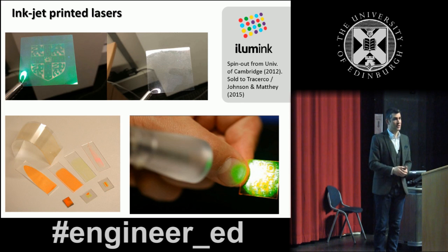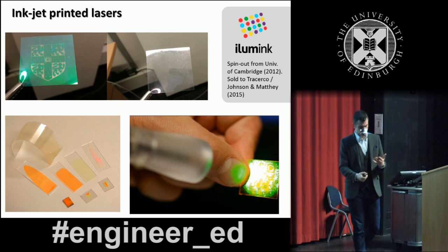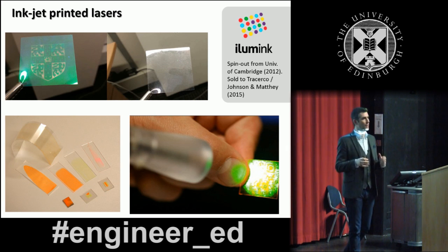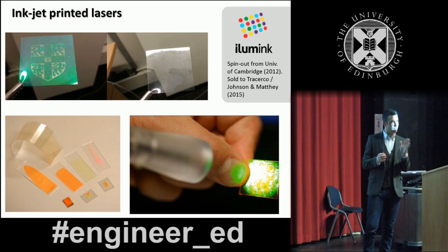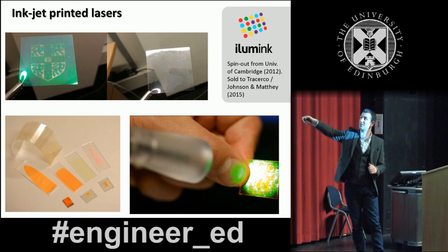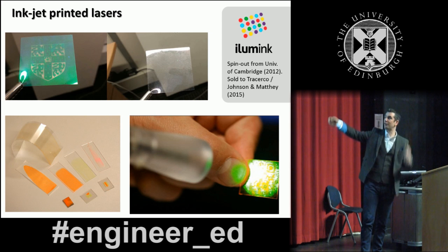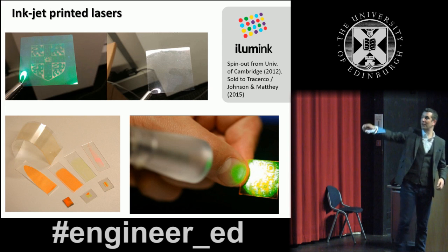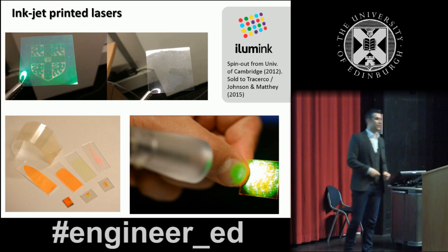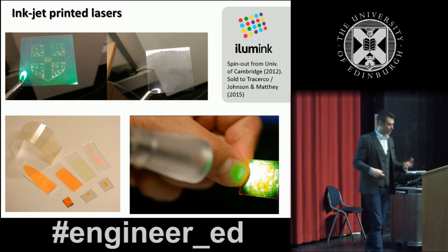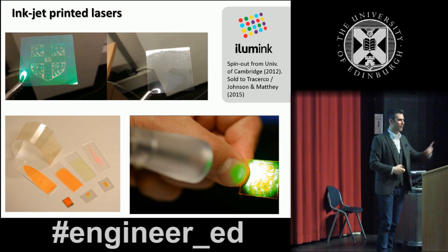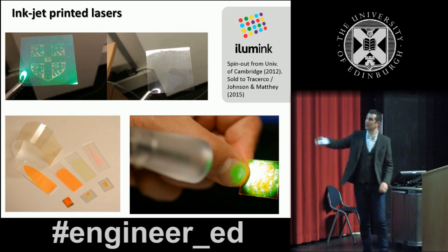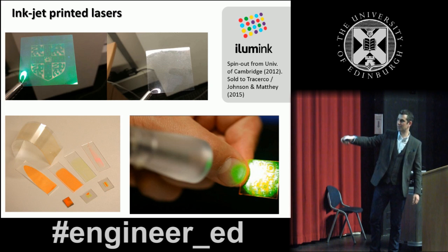So we can use it as a security coating, because the exact colour of reflection is going to be determined by the exact helical pitch of that chiral liquid crystal. And that's very difficult to replicate, because it's so intrinsically dependent on small concentration changes. And also, it's circularly polarised because of the chiral nature of that reflection property. It means that if we put a circular polarizer over the front of it, we can either remove or make visible that security feature. So that's a covert or overt, should I say, security feature. You might put it on high-value goods like a bottle of whiskey or a tax certificate or a cheque or something like that. We also paint them onto other materials like metal, glass, paper.